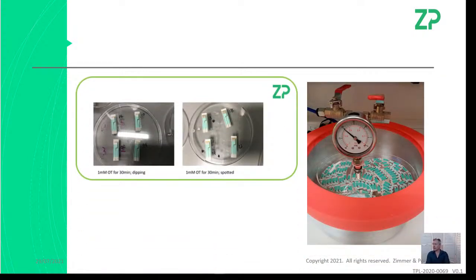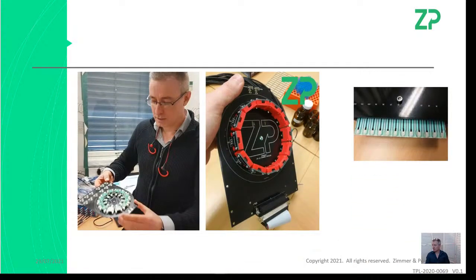It's also probably worth saying that when we're drying our materials, we don't necessarily just dry them at room temperature. We might actually put a slight vacuum, but what this tells you is we're really controlling the conditions. If you did a drop casting onto an electrode, and that drop casting dries in 30 seconds, that will give you one type of film. If it dries in 3 minutes, that's a very different type of film. So you do have to control the deposition and the drying of these materials that you've potentially drop cast on the electrodes.